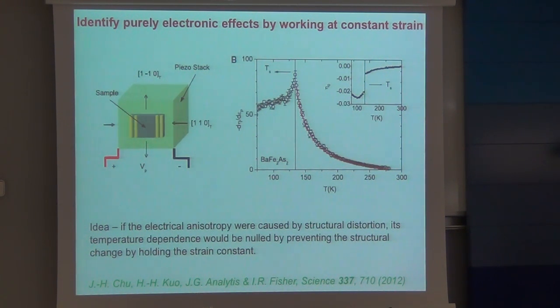And what they believe, they've got very good evidence from photoemission that what's happening in the pnictides is a form of ordering of the orbitals. So it's the outer orbitals forming the chemical bonds which are ordering and giving you the anisotropy, which is why you would motivate that that probably does couple very strongly to strain.